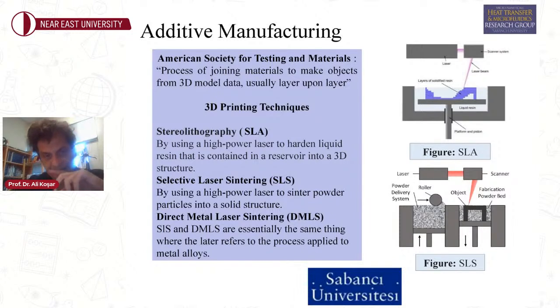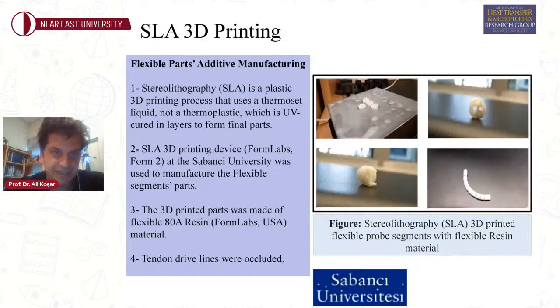And for fabricating the probe, we exploited additive manufacturing. And we used three techniques: one stereolithography, the other selective laser sintering, and for the final version, direct metal laser sintering, where we have the metallic probe, and we use this metallic probe in in vivo experiments. So we exploited three techniques.